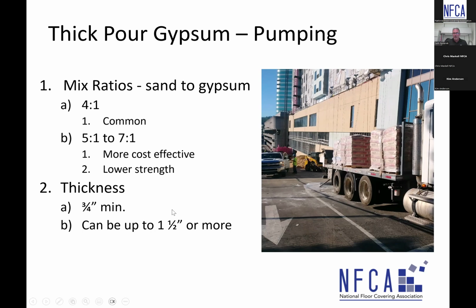As said earlier, very common minimum thickness: check with the manufacturer, but these thick pour gypsum products are typically poured a minimum of 3/4 of an inch in thickness, and they're typically poured up to 1.5 inches or more, depending on what the site requires.